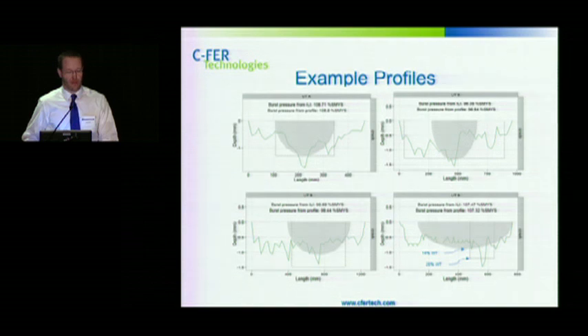There are 2 edges of the crack that were missed by the ILI tool. This is the case where if you look at the surface breaking length of the feature and compare that to what the ILI called, you would see a difference there. However, when you look at the burst pressure calculation, you see they're quite similar because the feature shape really matters in this case. So in this case, you have a feature that ends up very close to the unity line on the previous plot. On the top right and bottom left, we have 2 more examples of conservative cases.